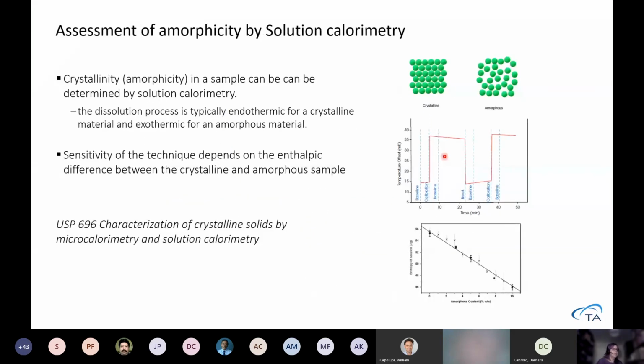The other method we have is solution calorimetry, where in the solution calorimeter, we put our solid sample in a small ampule, and we crush this ampule within a bulk liquid, and we measure the heat of solution. The solution process is typically endothermic for a crystalline material, and it will be exothermic for an amorphous material. So we measure temperature change, and that relates to how much heat is either produced or consumed while it's dissolving the sample. Then again, you will have to do standard curves, and the sensitivity of this technique will depend on how big a difference there is between the completely crystalline material and the completely amorphous material. If there is very little difference, you don't have a high sensitivity. If there is a big difference, you can get quite a good resolution of the data.